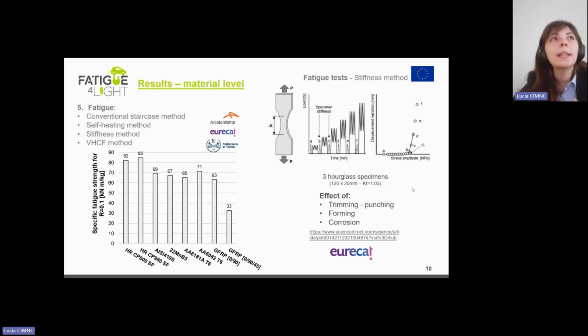And from this point of view, we've had the self-heating method, which was proposed by our partners at ArcelorMittal. We've had the stiffness method proposed by our colleagues at Eurecat. And we've also had an experimental campaign which was focused on very high cycle fatigue method, of course, with different failure mechanism, I would say, compared to the other behavior observed on high cycle fatigue specifically. And this campaign was done by our colleagues at Politecnico di Torino.